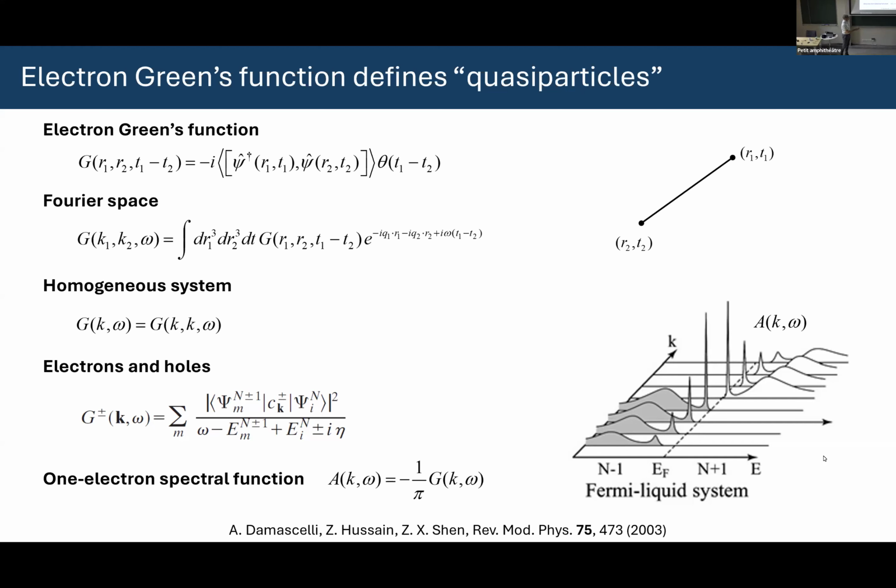They typically show pictures that look like this. But in a very interesting set of systems such as strange metals, this resonance doesn't really behave right. It doesn't have a width that goes like E squared. It'll just be linear in E. And then you have sort of marginal Fermi liquid stuff going on that we're going to start talking about today in my next talk, because I have to give 2 talks.